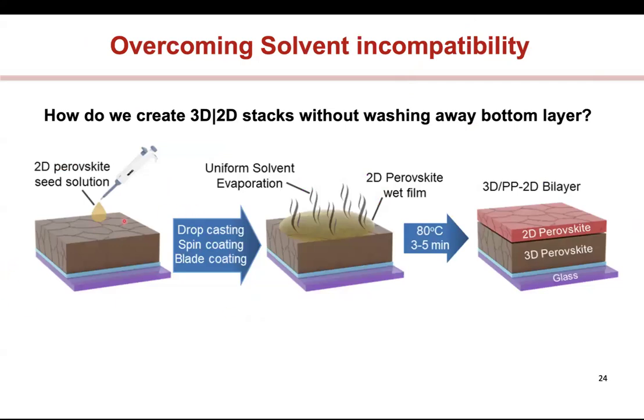And so one of the issues that we always run into when you do solution processing, and maybe some of you have done this, is that if I have a film of 3D perovskite, and if I want to put down another layer on top, and if that's also a perovskite, then I have to worry about the solvents that I use, because I don't have solvent compatibility. Because this is after all also a perovskite, which means whatever dissolves a 3D also dissolves a 2D. And so when I mix these 2D and I put this on, using this memory seed method, the chances are that I will dissolve away this 3D perovskite which is underlying. Okay.